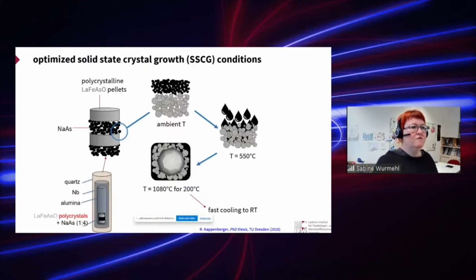So if we now put all our parameters together, it turns out that if we have 1111 polycrystals pressed into pellets, mix them with sodium arsenide in a ratio of 1 to 4, put it in such a crucible assembly, then at ambient temperature we have solid sodium arsenide and solid pressed pellets.